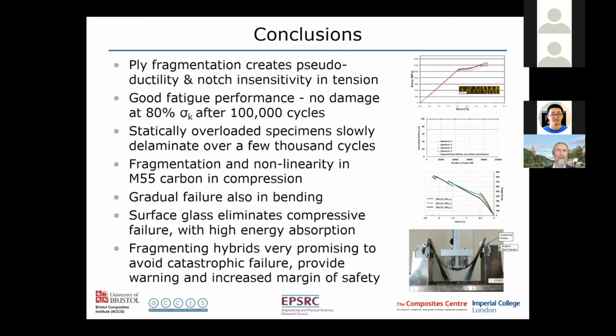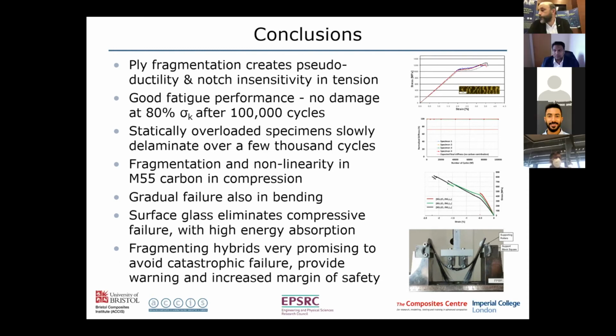So the high strength fibers that we use for quite a bit of the work I've shown today normally have a failure strain of about 1.6%. Well, it's about 1.8% if you measure it very carefully with a good test. But actually, we find in the hybrids, if they're very thin and we have only a single 0.03 millimeter ply, that 1.8% failure strain goes up to 2.3%. So a very substantial increase in the failure strain.